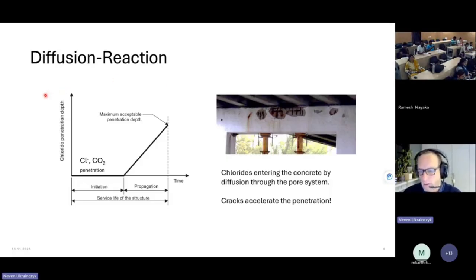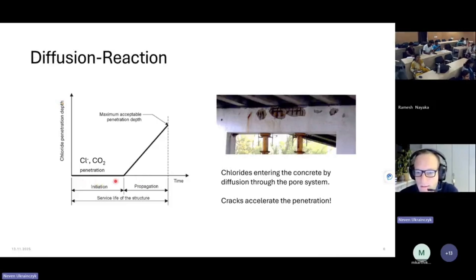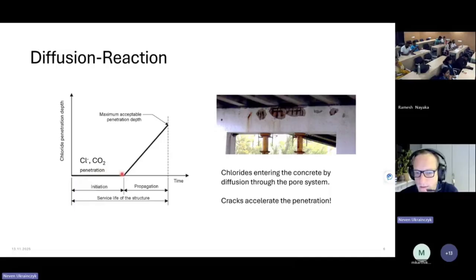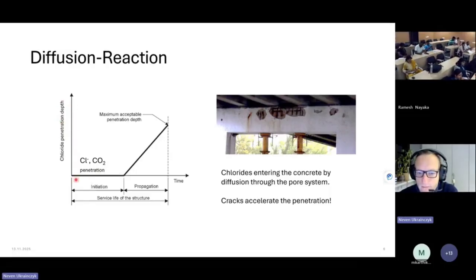But that was mostly, they say, because of errors during the design phase and the construction of the bridge. So this is a very important issue also, and we have the penetration of chlorides through the concrete cover. This is the initiation phase. We have the chloride penetration depth, how deep it comes.